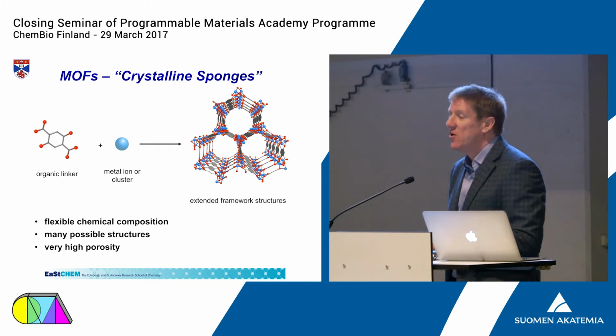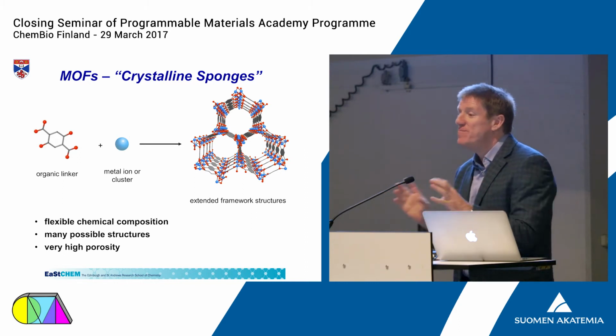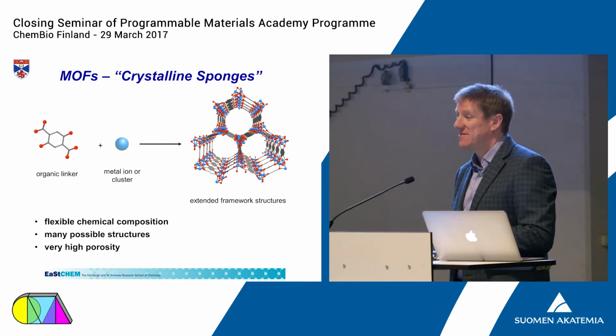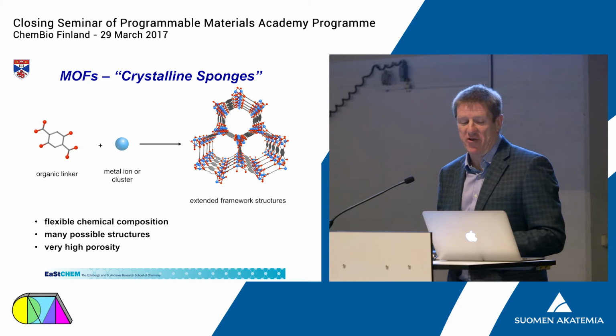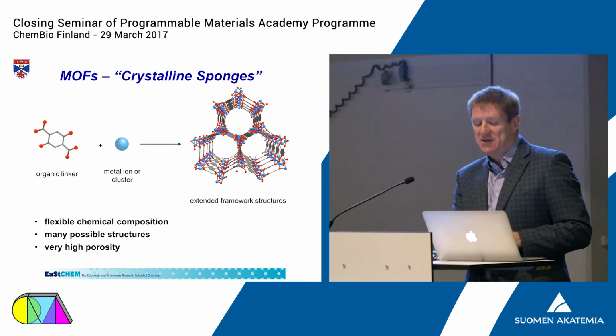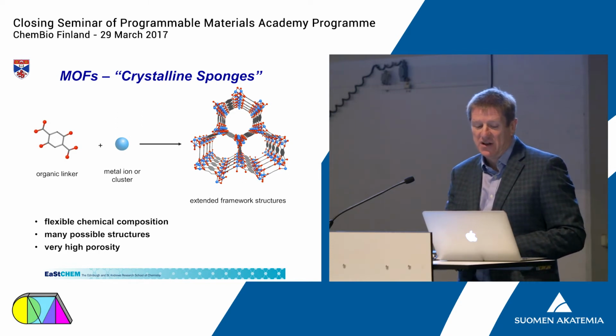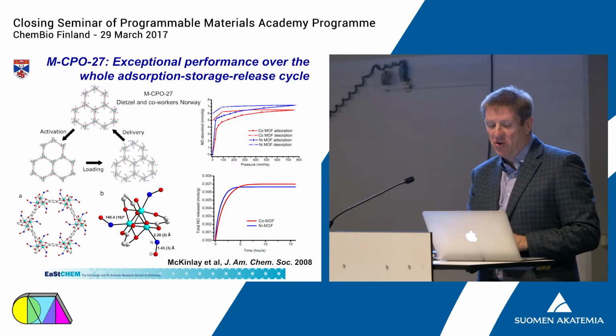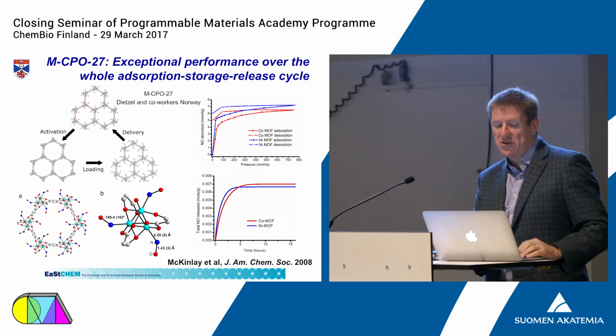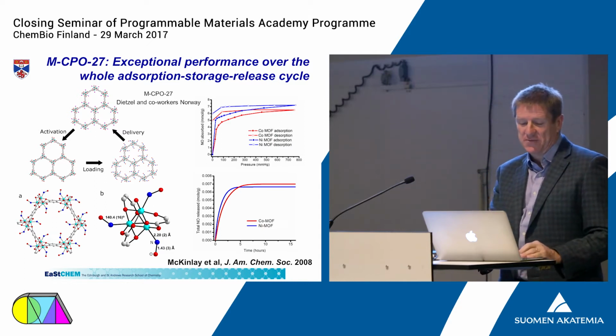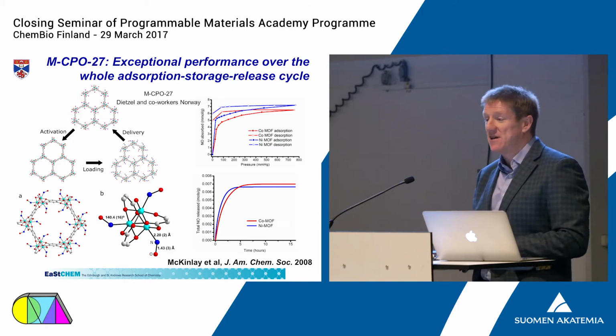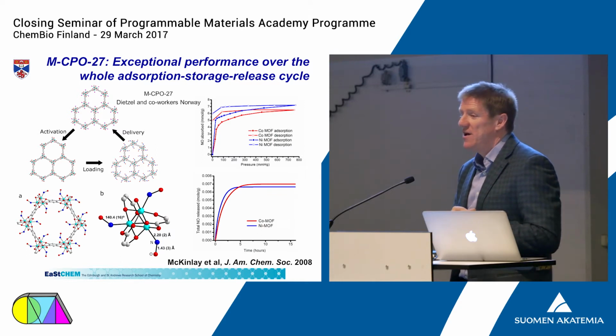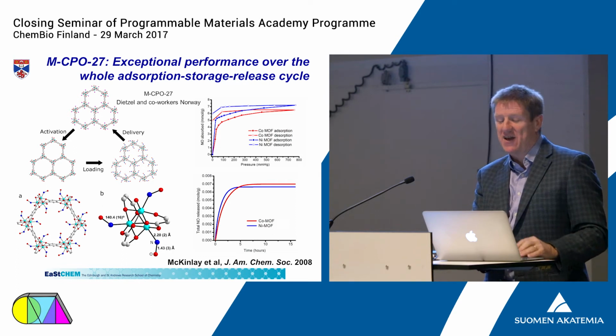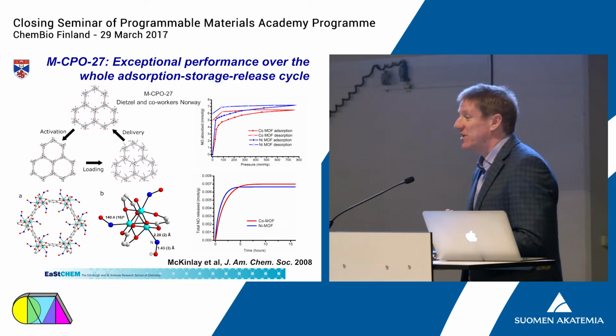What about metal organic frameworks? Well, they are even better at storing and delivering gases like nitric oxide because they've got much more surface area, and they also have metals. This is a particular type of metal organic framework, which I'll call CPO-27. It's got a very high porosity, and it also has metals at the corners. So this site here, six of them around this hexagon, is a metal site that, when you make it, just has water attached to it. You can heat that up, get rid of the water, and leave a metal site there that's perfectly arranged to bind something like nitric oxide.